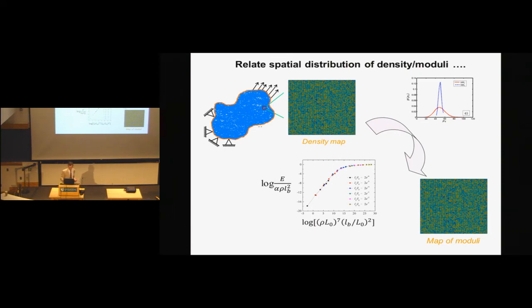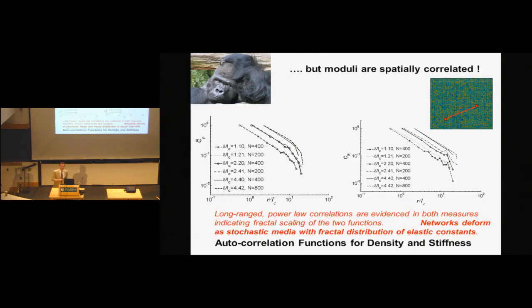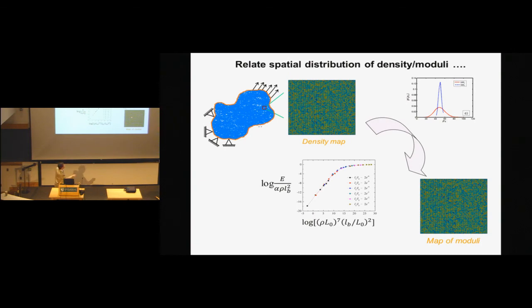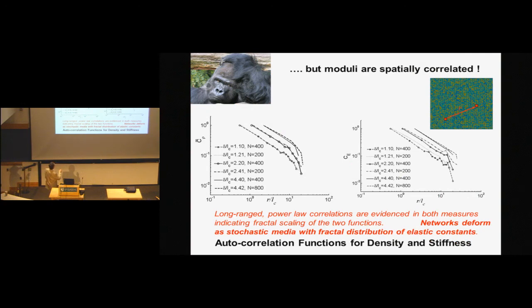Can I do that? Well, the answer is yes and no. So you may get a headache. Why? The moduli, that is the map of elastic moduli I'm showing over here, are actually spatially correlated, meaning that the modulus at some site depends on the modulus at another site. I don't want to get into the details of it, but both plots show spatial correlation functions of density and moduli. The horizontal axis is distance. So basically what these functions tell us is how correlated the density at this site is to the density at that site.